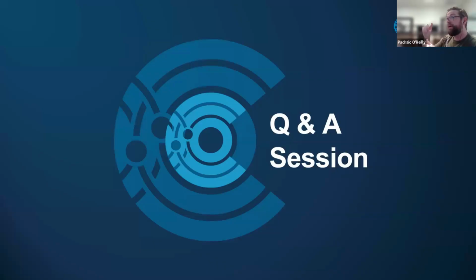However, if you're looking at very tall features with a high aspect ratio, as the tip is going up the edge of these tall features, obviously the tip will not be quote unquote engaged with the sample at these, so you will get a drop in the PiFM signal along these sharp edges. But then across the surface, there will be no issues.